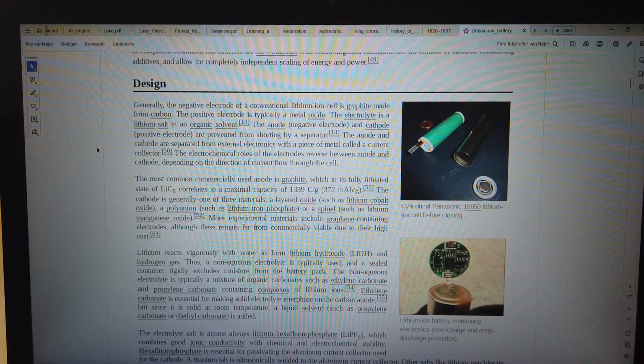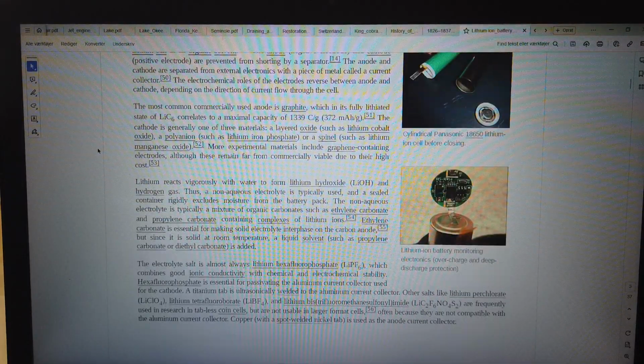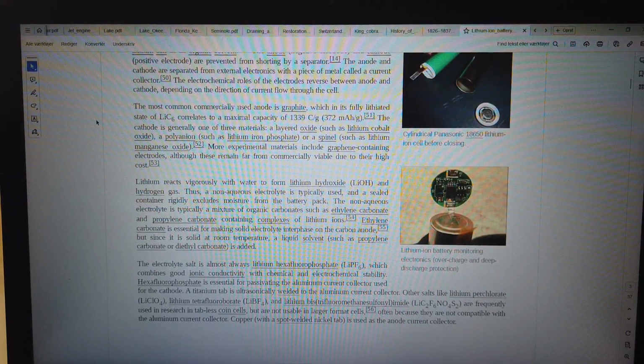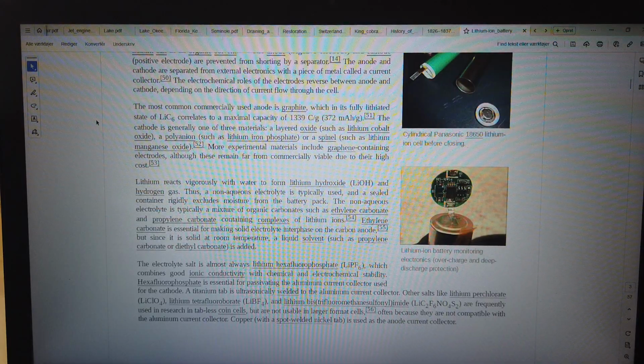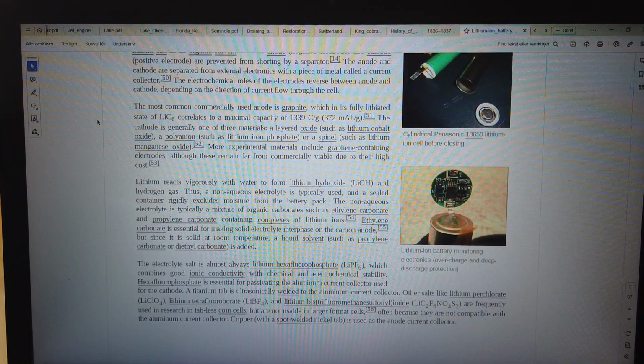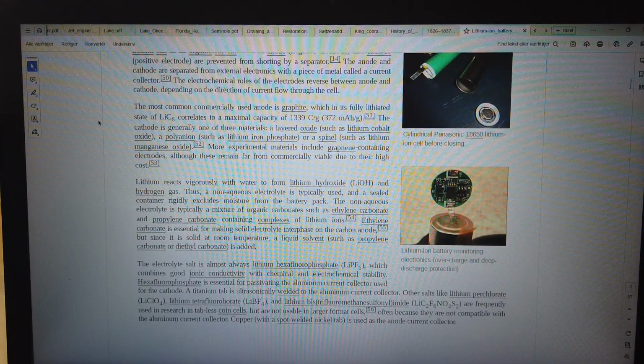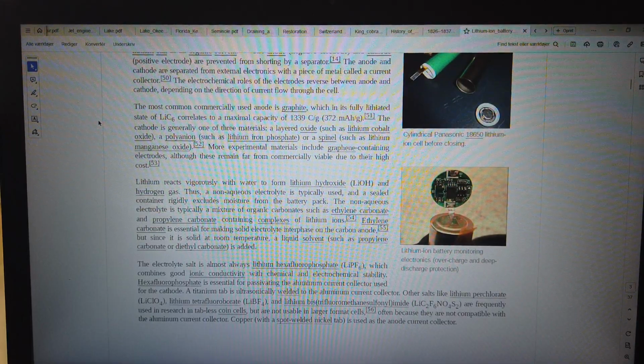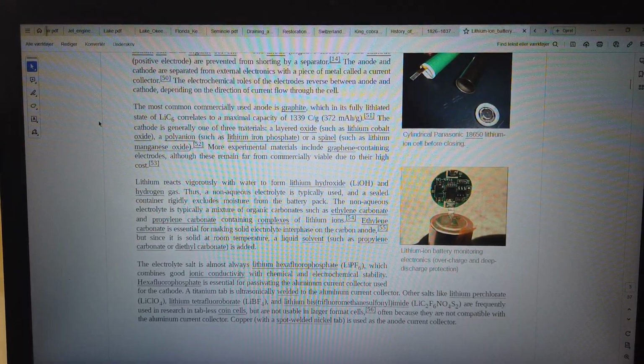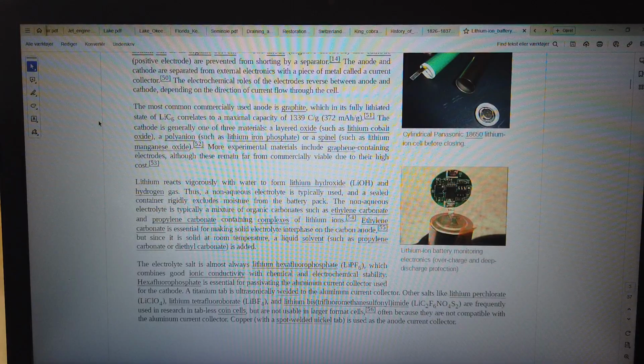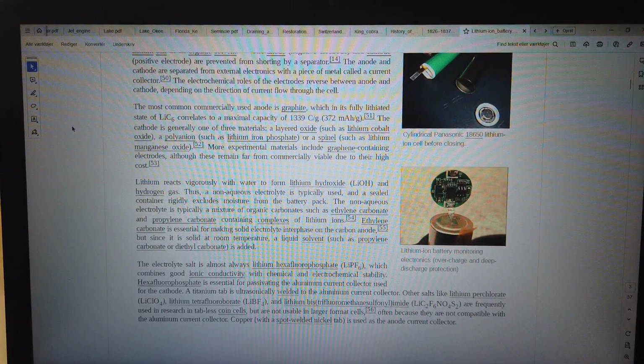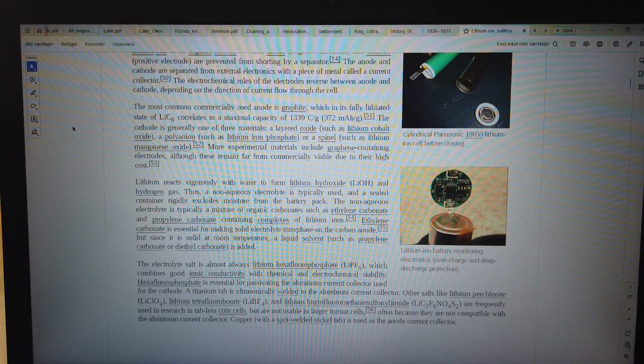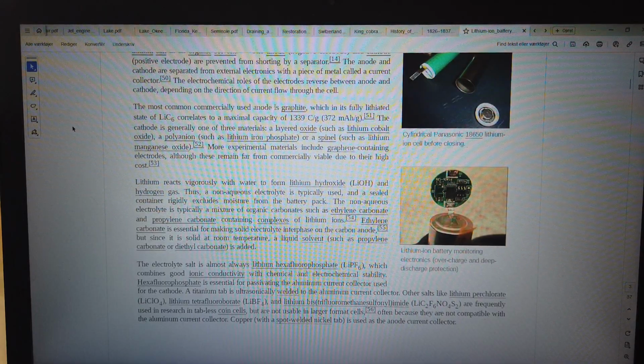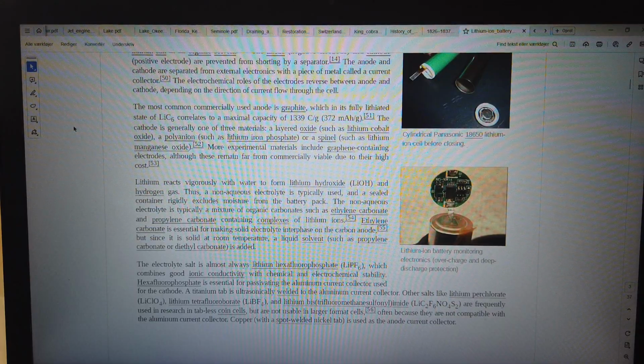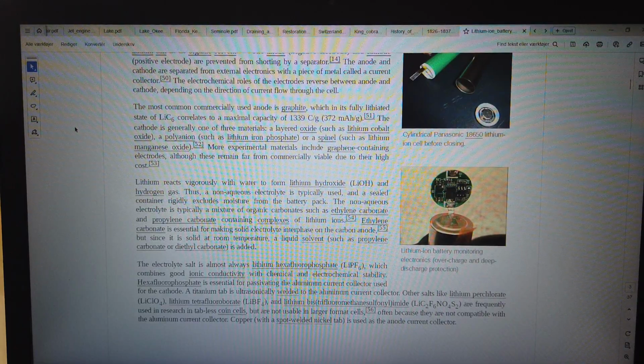the cell. The most common commercially used anode is graphite, which in its fully lithiated state of LiC6 correlates to a maximal capacity of 1339 C/g, 372 mAh/g. 51. The cathode is generally one of three materials: a layered oxide, such as lithium cobalt oxide, a polyanion, such as lithium iron phosphate, or a spinel, such as lithium manganese oxide. 52. More experimental materials include graphene-containing electrodes, although these remain far from commercially viable due to their high cost.